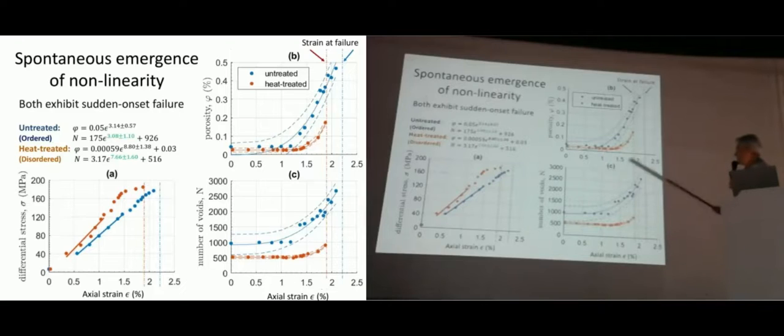And what we see is that the porosity increases with this inverse power law. And then bang, it goes bang at the failure time. So that would be a hard failure time to predict from these data. There's no obvious singularity, because we're still dealing with relatively low porosity materials. And it turns out that it's very hard to predict the onset of sudden catastrophic failure in these systems.